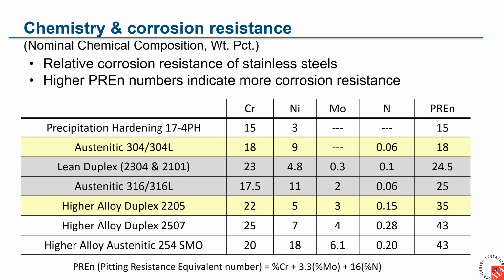The higher the number, the more corrosion resistant the stainless steel. So more chromium, more molybdenum, more nitrogen, all increase the corrosion resistance. Nickel helps us with welding and impact resistance, among other things. Here you can see the precipitation hardened stainless steels have the lowest PRE and the lowest corrosion resistance. We have a step upward with 304. Then we have the lean duplexes and 316, around 25.